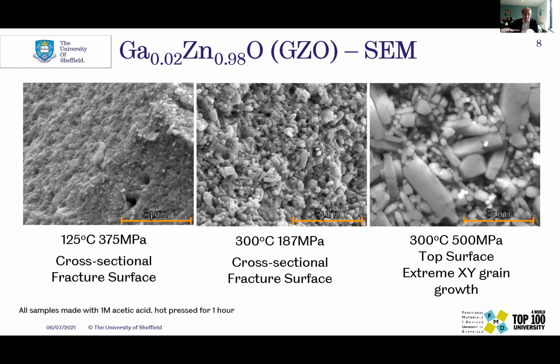Just a factor of note on the far right, this is a top surface view. When we increased the pressure significantly, we suddenly got a constriction effect, which caused enormous grain growth in the XY direction, which sort of counteracted the usual slight increase in Z direction growth you get with cold sintering sometimes observed.